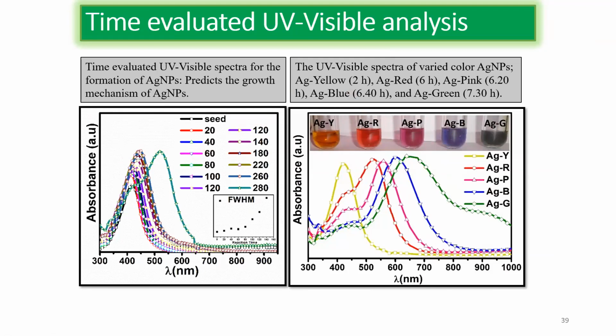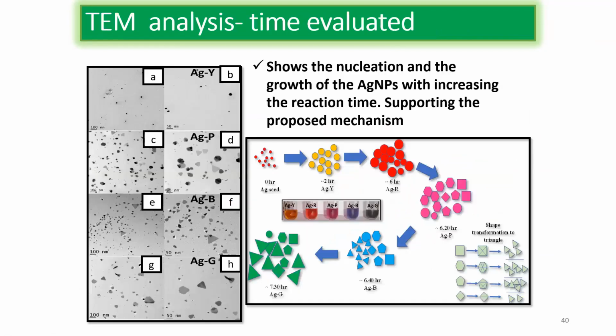We can get it. And after that, in the same study, I found out why this color change is there. So I took 10 images of all these different colors of silver nanoparticles, and what we found is that the spherical nanoparticles give some octagonal particles in the pink, and in blue we found some rods and some triangles, and in green I found that only triangle nanoparticles are there. So based on that, I made this scheme of how the particles change with time.